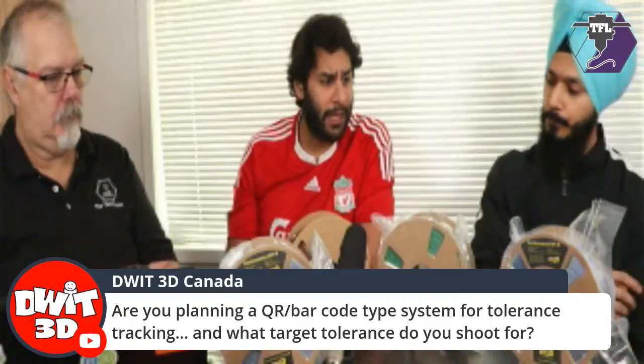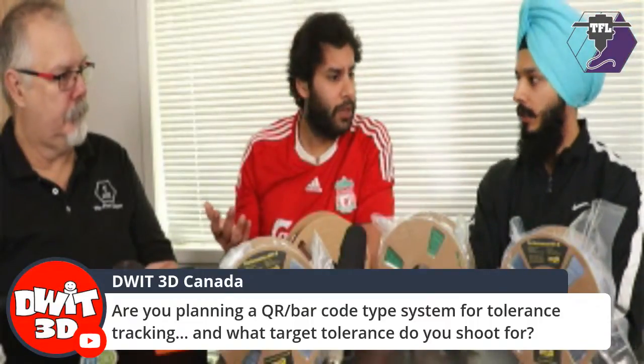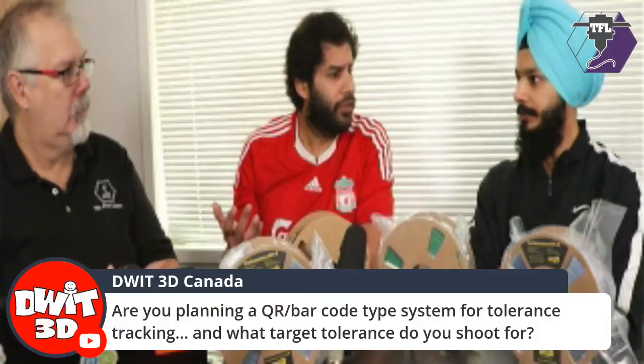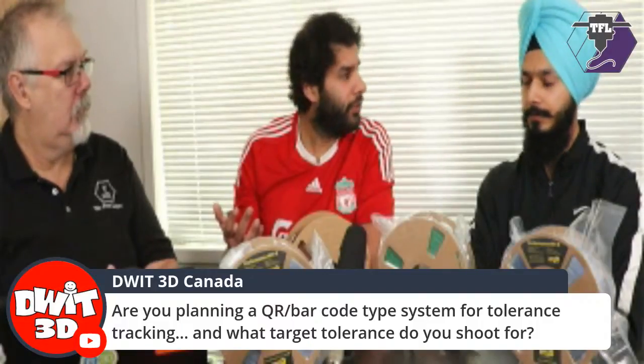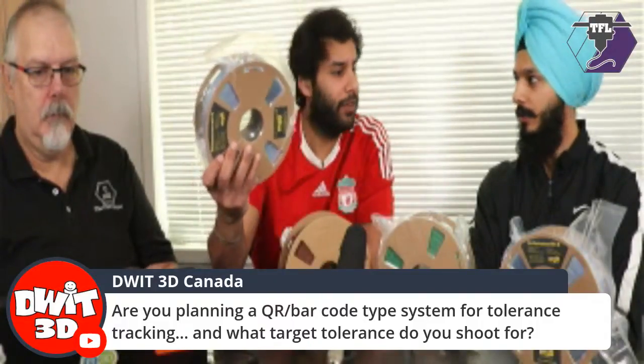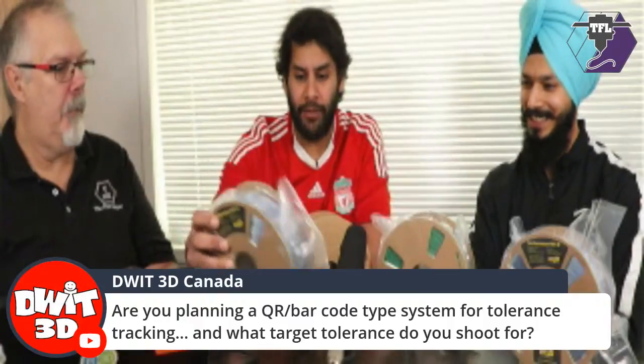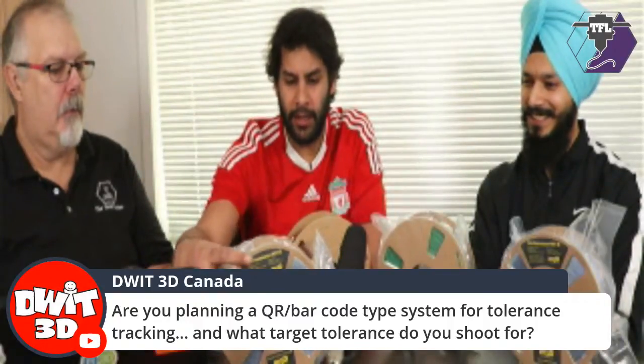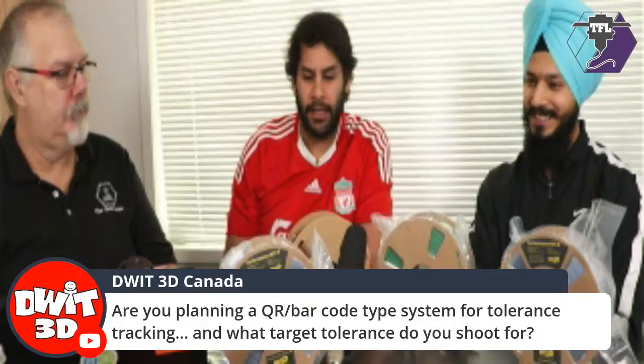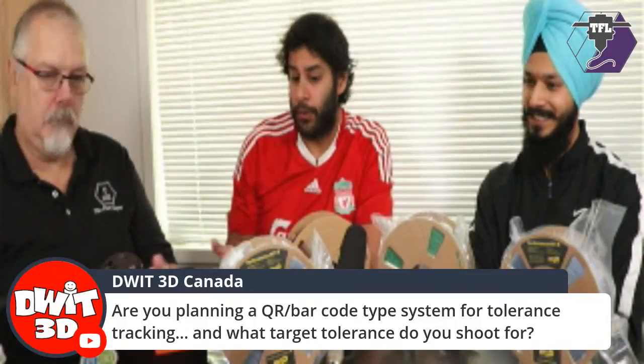For example, when we were making the PETG, as we were troubleshooting, we must have discarded 20 or 30 kilos easily. We were like, we can't use this. And to get about 50 kilos of this, we almost wasted half. But it's not a waste, because what we're going to do is pelletize it back down and just re-extrude it, because it's virgin grade material.